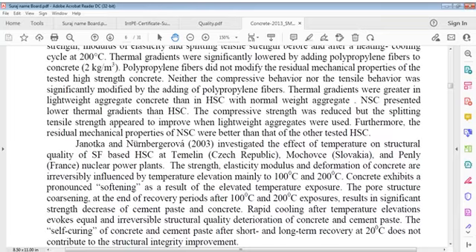Thermal gradients were greater in lightweight aggregate concrete than in HSC with normal weight aggregate. NSC, normal strength concrete, presented lower thermal gradients than high strength concrete. Compressive strength was reduced, but splitting tensile strength appeared to improve when lightweight aggregate was used. Furthermore, residual mechanical properties of normal strength concrete were better than those of other tested high strength concrete.